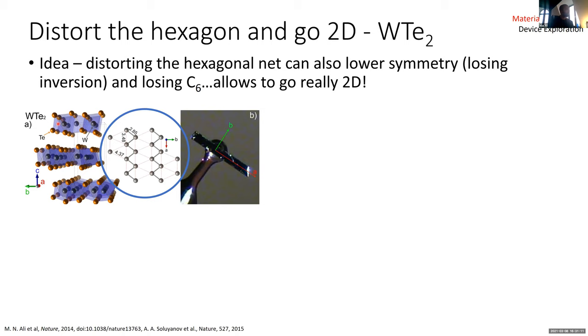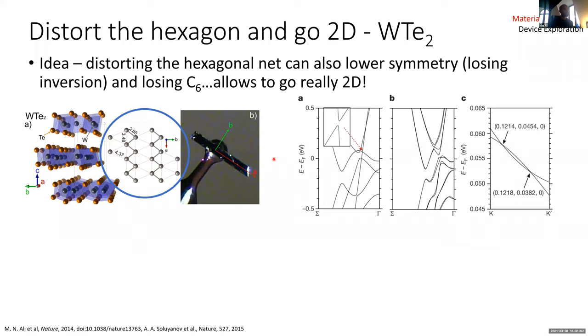Basically, due to a trick of chemistry, tungsten and tellurium happen to have very, very similar electronegativities. Tungsten is special. It behaves not like its neighbors in the heavy transition metals. And it likes to bond with itself, which is exactly what happened here. We got a zigzag chain of tungsten. And that is what distorted the hexagonal tungsten net. And so it ends up being orthorhombic, and it grows in this beautiful layered shape. And as expected, to some extent, the lowering of the symmetry did indeed keep some interesting aspects, some remnants that persisted in the electronic structure.